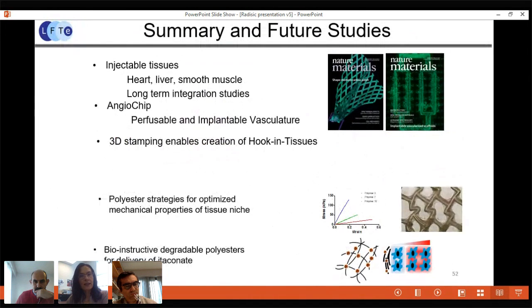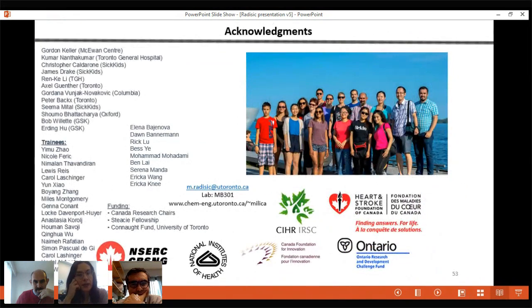And so in the interest of time, I'll just skip to the next slide and summarize. I showed you several important technologies from our lab, and those include injectable tissues that are all demonstrated here, angiochip, and 3D stamping for creation of hook-in tissue. So that's a family of technologies that we developed with POMAC. And then by starting to change monomers in what was essentially chemistry that was described for POMAC, by adding another tricarboxylic acid, or by adding a dicarboxylic acid such as itaconate, we are able to further tune elasticity of these polymers, as well as to tune degradation rate and to tune the host response of the body to the polymer implantation.